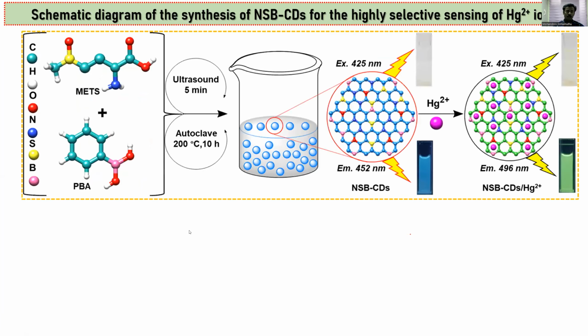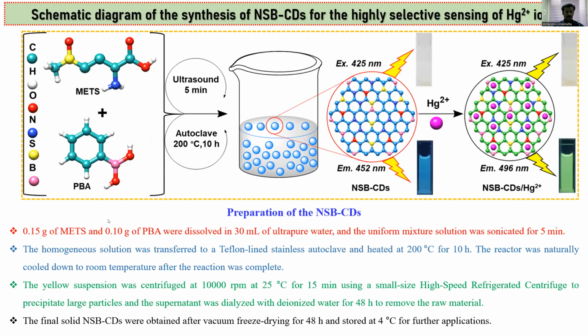Previously I explained the same procedure, with a little modification because here I have used 2 different precursors. The first one is methionine and the other is phenylboronic acid. This is important for doping with boron. Previously we checked nitrogen and sulfur only. Here I have doped the carbon dots with multiple heteroatoms, using phenylboronic acid. So we can confirm this from the synthesis studies.